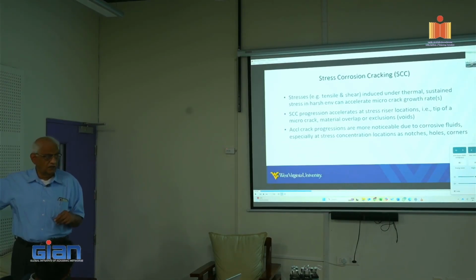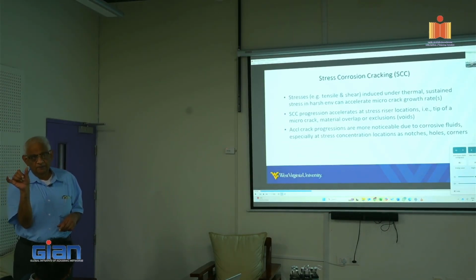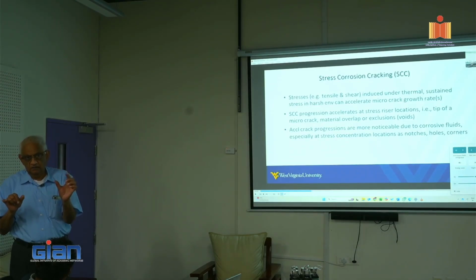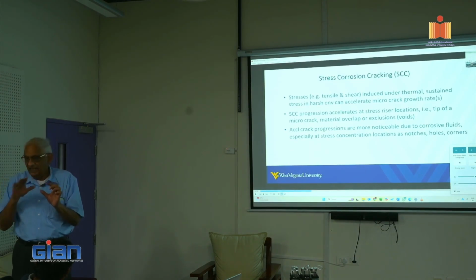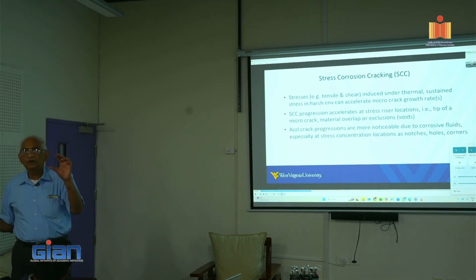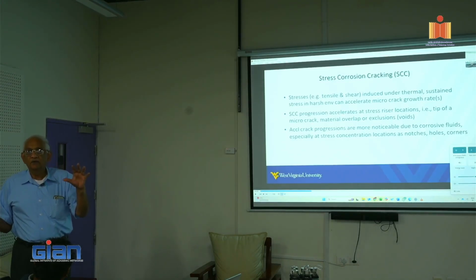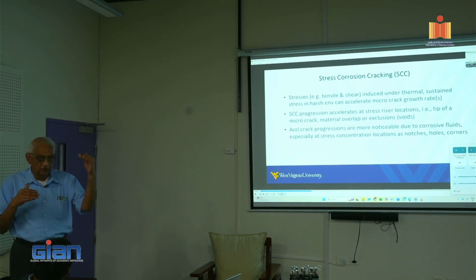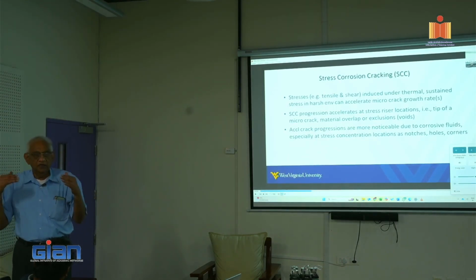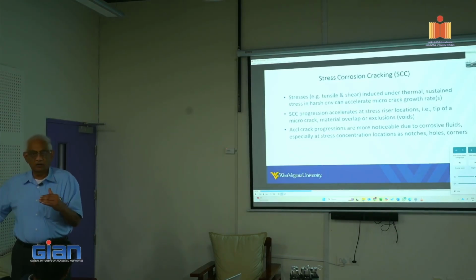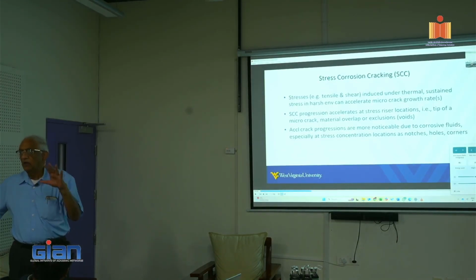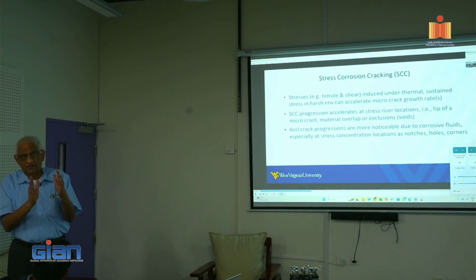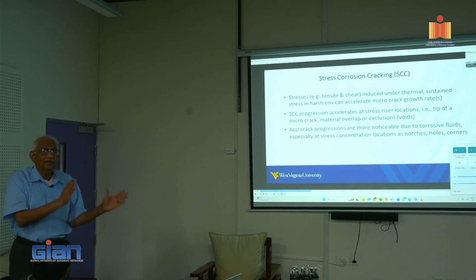Therefore, in this curve, I'm going to fit a certain portion of the curve from the natural aging and then extrapolate how long that would survive. I wrote a paper, got good reviews on this. So if I demarcated the procedure steps, A, B, C, D, E, F type step. So again, if you send me an email, I'll be happy to share that paper. In other words, in short, you cannot extrapolate aging based on the accelerated lab testing without a portion of that is properly correlated with the natural aging.